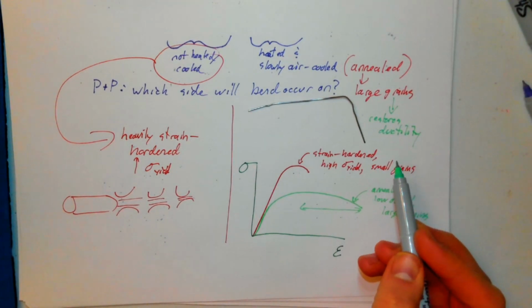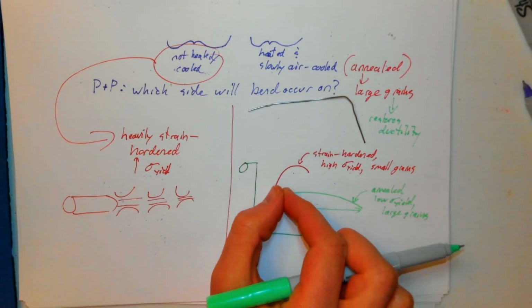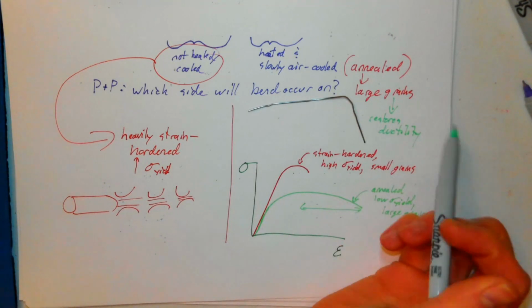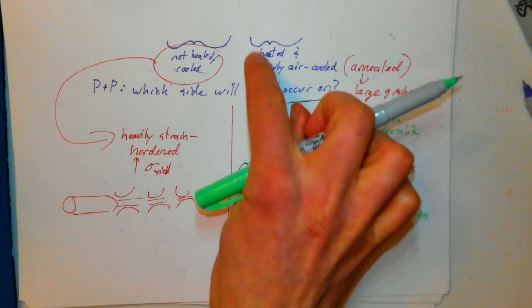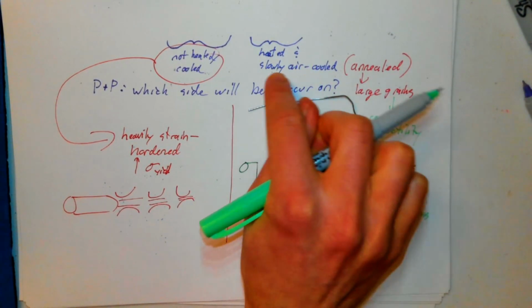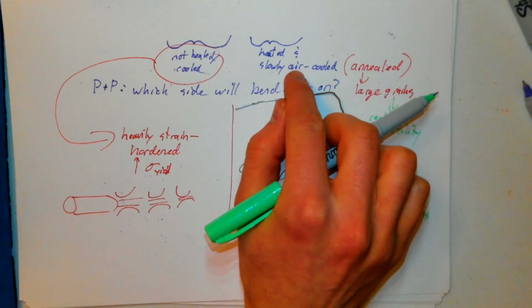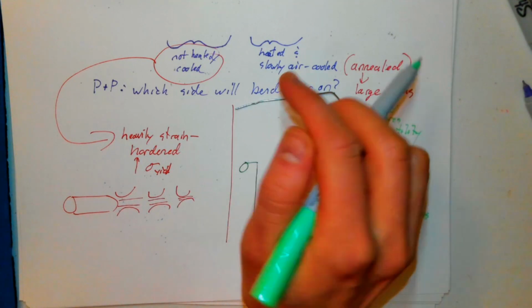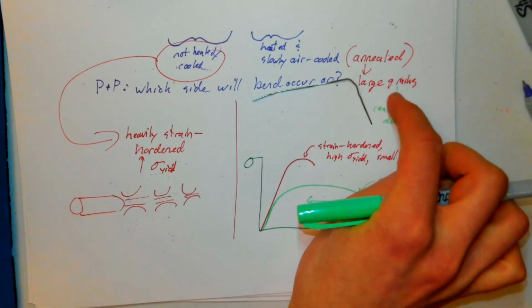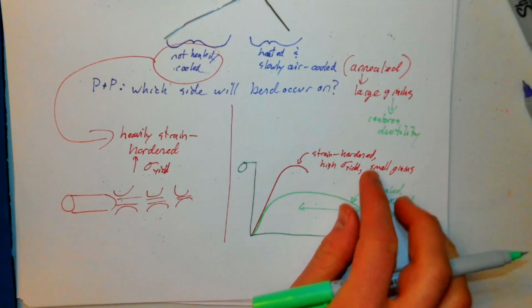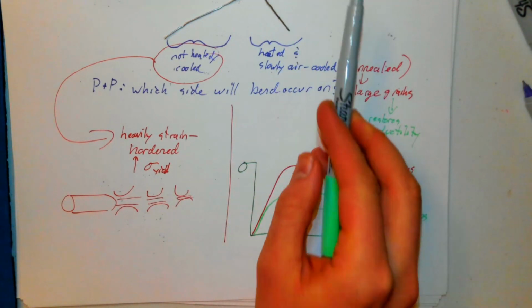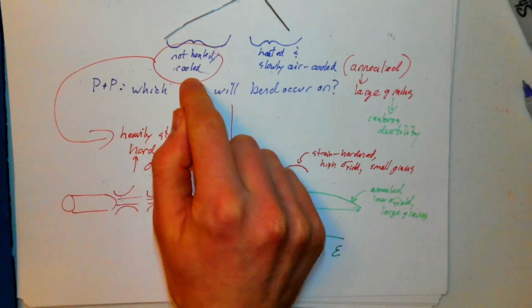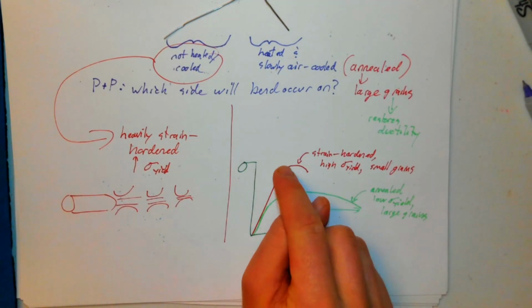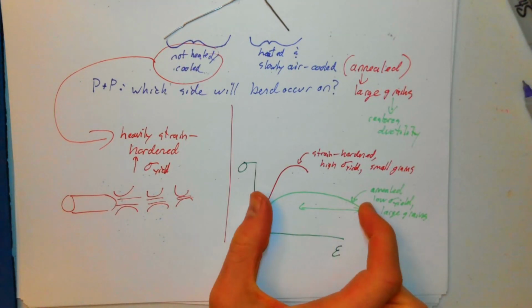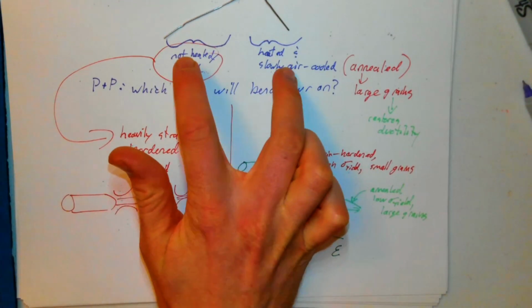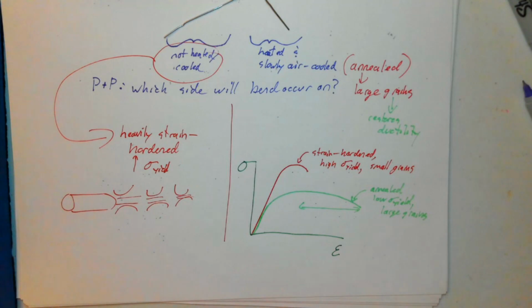So in some applications where it's not important to have a high yield stress, but rather it's important to have a lot of toughness, sometimes what people will intentionally do to their metals is they'll do this process on purpose. They'll heat it and cool it slowly, maybe not air cool it, but over the course of several days or even weeks in precisely temperature controlled ovens to basically restore ductility. So under some applications, for example, the blacksmith quenching the sword, you don't care about ductility and you want a high yield stress. Under other applications, we don't care about a high yield stress, but we want a lot of ductility. And whether you heat or cool your metals quickly or slowly gives you that choice.